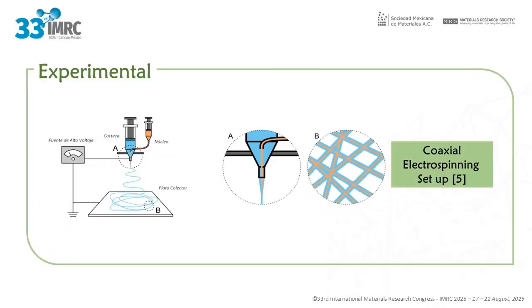To obtain the composite nanofibers, coaxial electrospinning was used, a technique that allows two solutions to be processed simultaneously using concentric needles, one for the core and one for the shell. In this case, titanium oxide forms the shell and copper oxide the core. The coaxial electrospinning system includes a high voltage source, syringes with polymer solutions, needles connected to the voltage source, infusion pumps that control flow, and a collector connected to the source which receives the formed fibers. Coaxial electrospinning consists in applying a potential difference between the concentric needles and the collector, which stretches the polymer solutions, forming a continuous thread composed of different materials, as shown in this image.